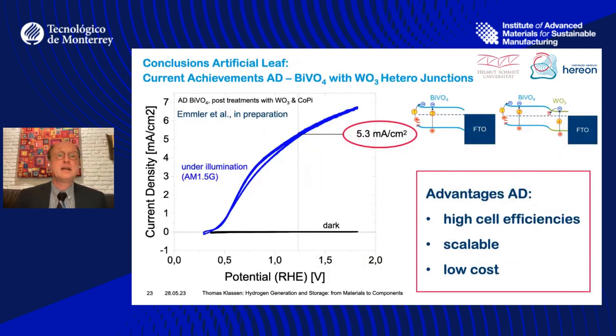Okay, so finally, for this, let me just show you our most recent results. We have been able to achieve 5.3 milliamps per square centimeter as photocurrent for co-deposited tungsten oxide and bismuth vanadate.